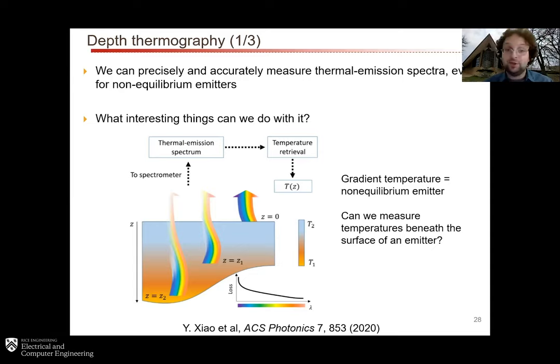And that doesn't have to be a thermal emission measurement. So Kirchhoff's law applies to many, many objects. And so if you do reflection or transmission measurements, then you can get a pretty good idea of what the emissivity is without having to do thermal emission measurements. So there's another question that came up here, which is, what emissivity standards do you use?